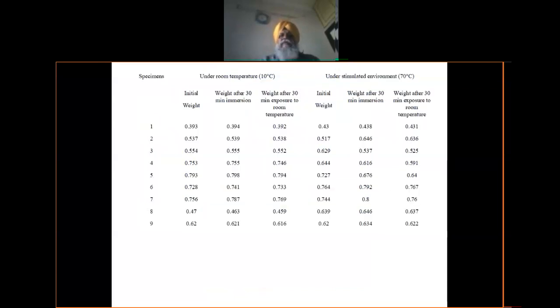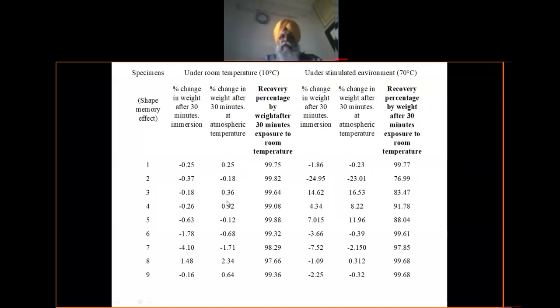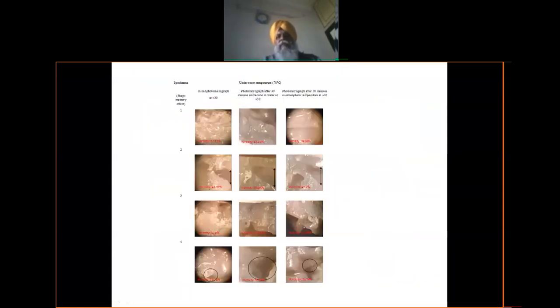Then we tried to see what is the effect of a lower temperature, that is 10 degrees, and 70 degrees Celsius temperature, on the weight and on the volume. So what we observed under those extreme temperature conditions, the recovery rate was something around 99, sometimes more than 99%. And then we tried to see why this is the effect. So we tried to see their porosity. We observed that once we were working at these two extreme temperatures, the material is having a controlled porosity, which is more understood from this particular image, where the porosity control is better, right?